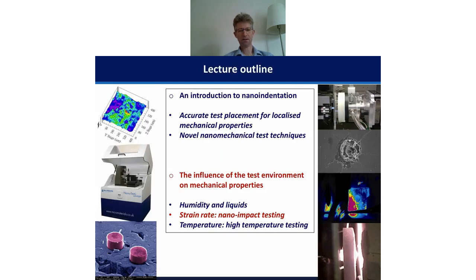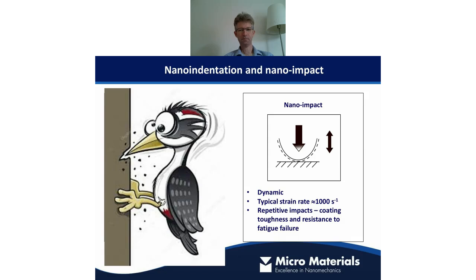Okay, so moving on to the next subtopic. Now we're going to look at strain rate, and we look at that through nano impact testing. In comparison to an indentation test, which is essentially a quasi-static test, in an impact test we now have a dynamic test. Instead of the load being applied very slowly, we're applying that load very rapidly, and we can achieve strain rates of about 1,000 per second, which compares to a normal quasi-static indentation where you would typically be at about 10 to the -2 per second. So you're many orders of magnitude higher.